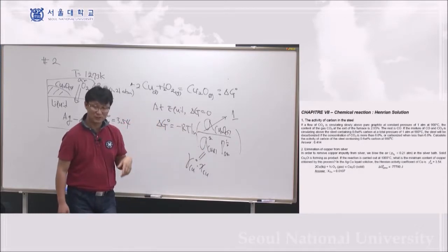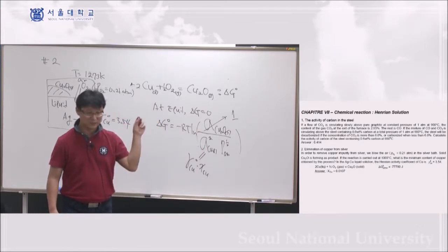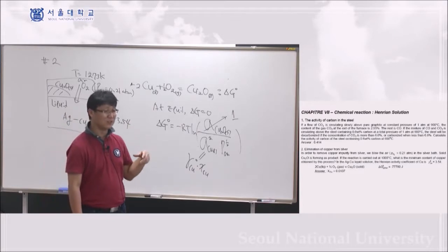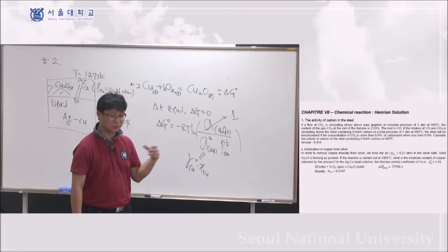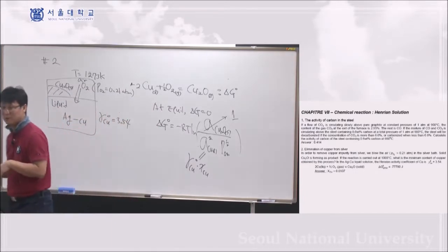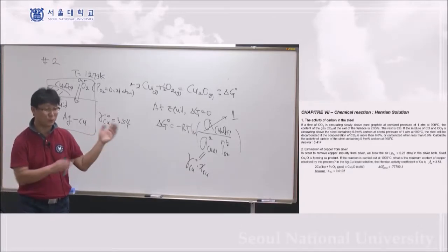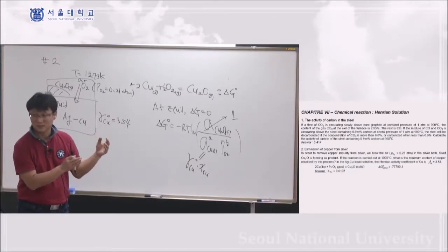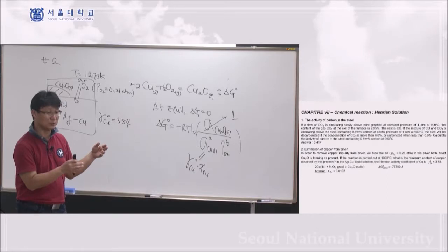And so typically, instead of using air, they are adding enriched air. Enriched oxygen, enriched air, or pure oxygen. Pure oxygen is a little bit dangerous. But industrially, you can easily make about 36% or 40% O2 gas. That's easy to handle too.